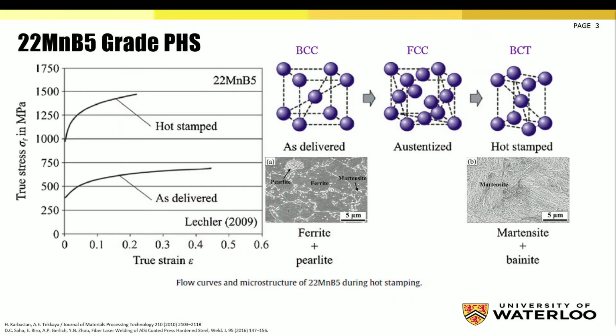Now, 22 Mn B5 is the most commonly used grade of steel for the production of tailor-welded blanks because after the hot stamping heat treatment, the steel exhibits a tensile strength of about 1500 megapascals and a yield strength of about 1100 megapascals as shown by the flow curves.